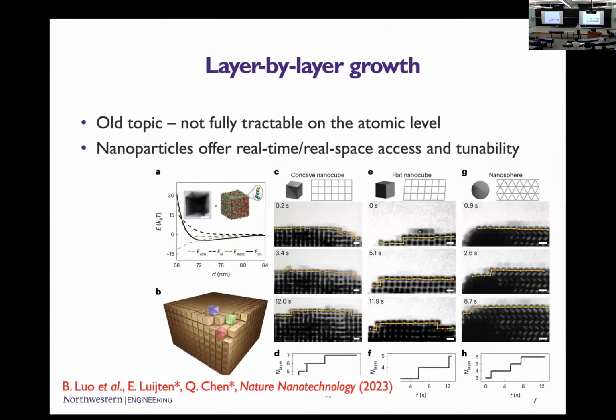And this really depends strongly on the interaction range. If you have, let's say, a little cube that's sliding on this table, and it needs to fall off the table to extend this layer that is formed by the table, it really depends on what the interaction range is. Because at the moment that something drops off a cliff, it is temporarily more or less detached from the island. To which degree it's detached depends on how long the range of the potential is. So this is where colloids that you could be studying are very different from the atoms that we are interested in.